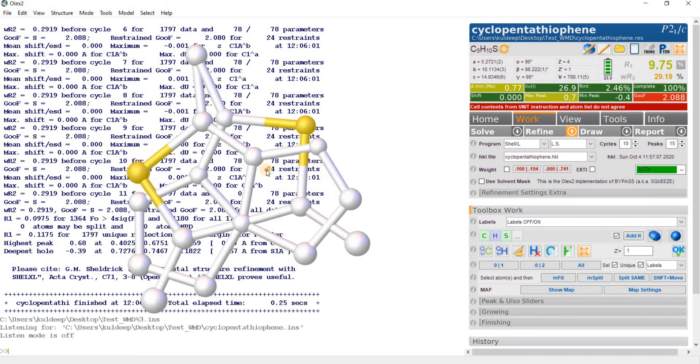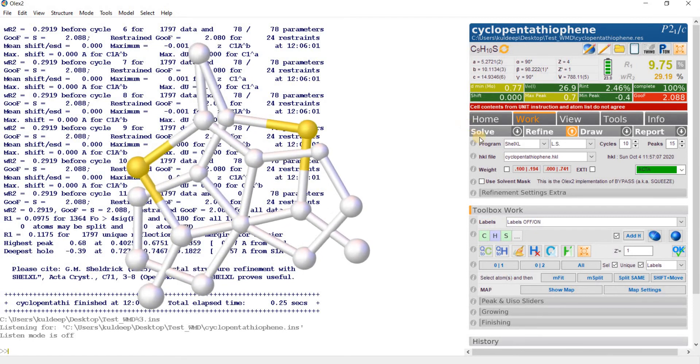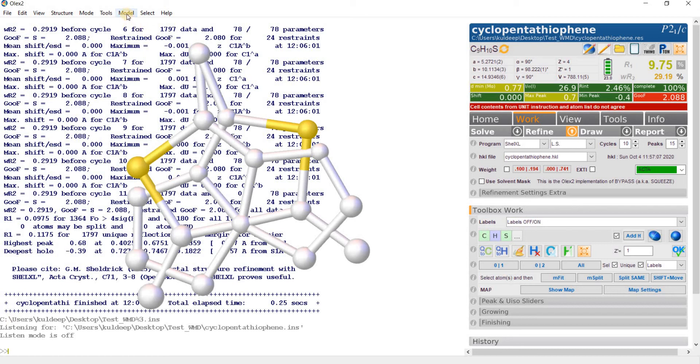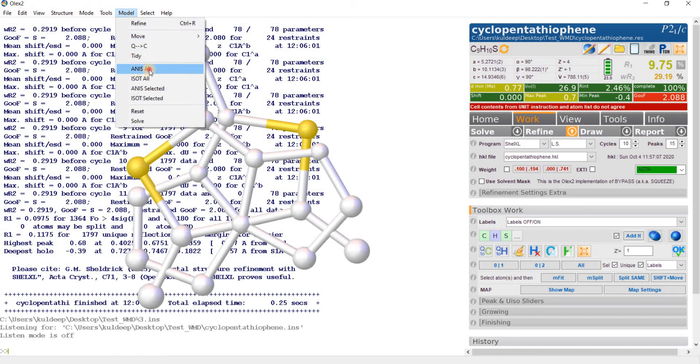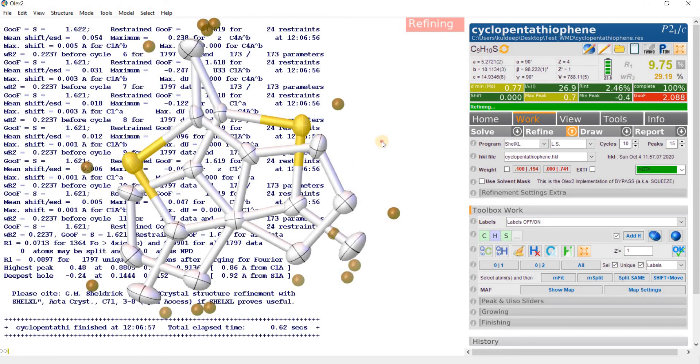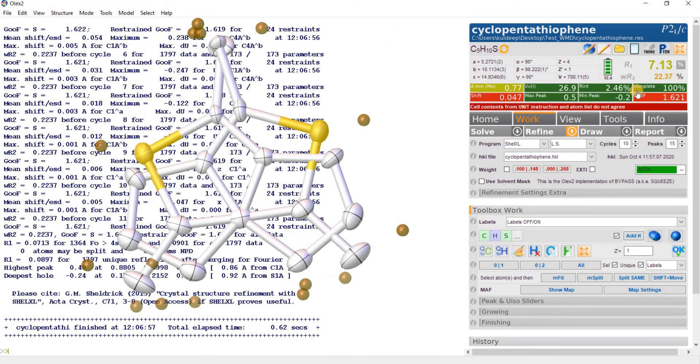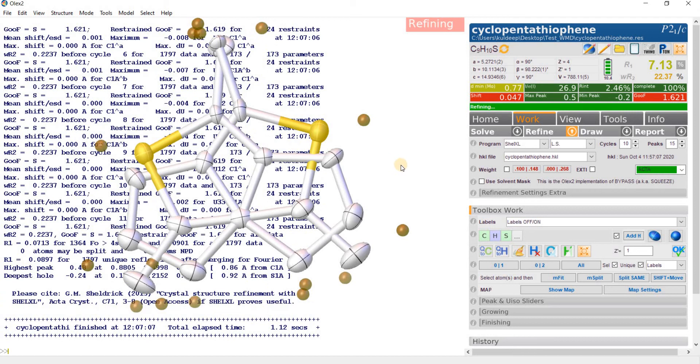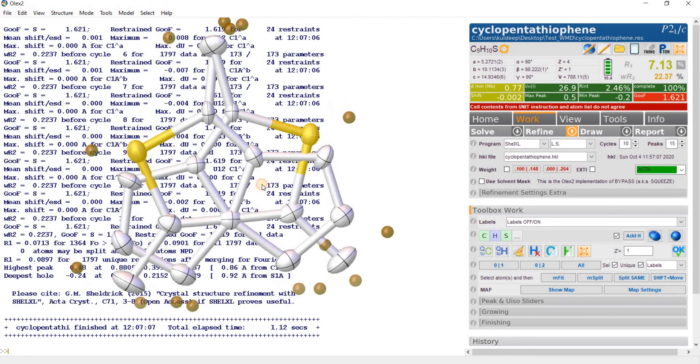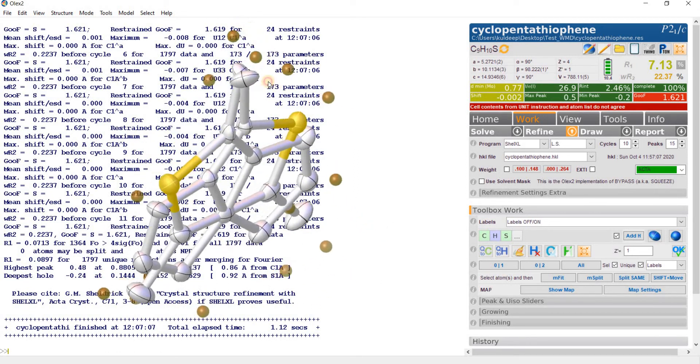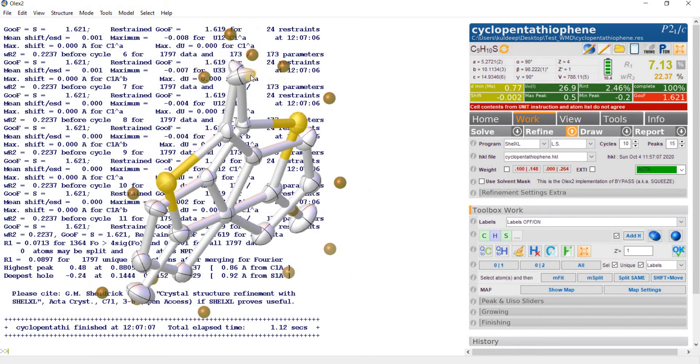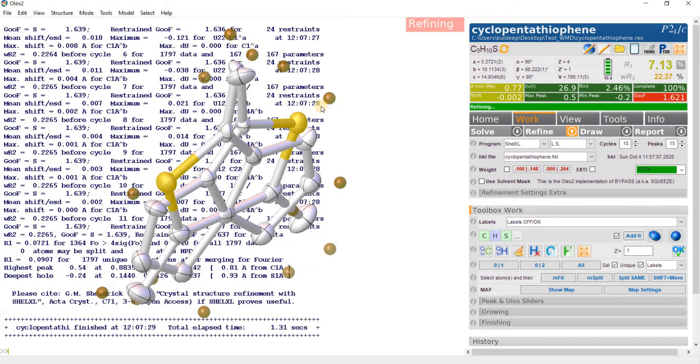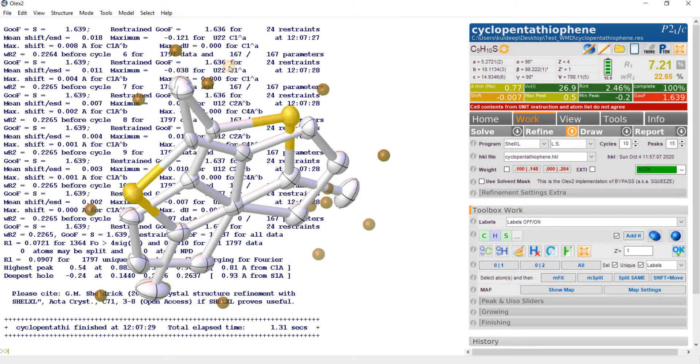Now the molecules seem to be very good. All the thermals are reasonable. The R-factor is dropped from 35 to 9.7. The shift is also stabilized. Let's refine one more time. We are getting the two components, two disordered components. The maximum abundance is only 0.7. There is no need to type the restraints manually; it will write all the restraints automatically in the INS file.